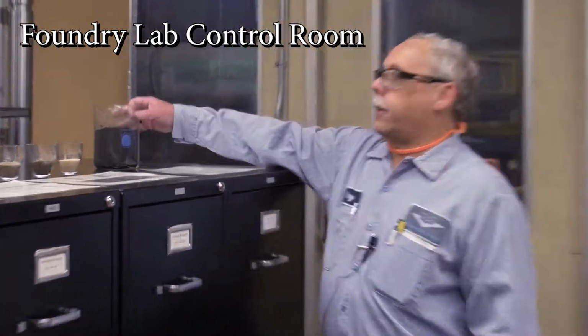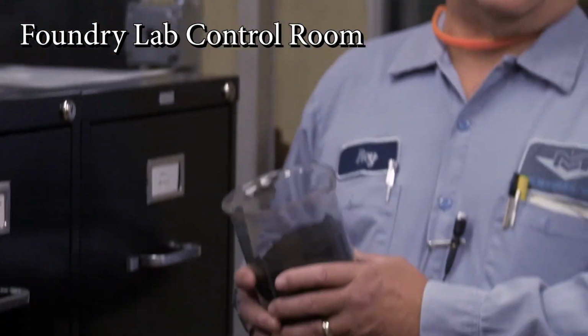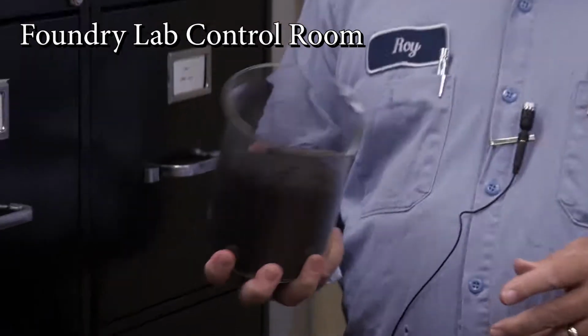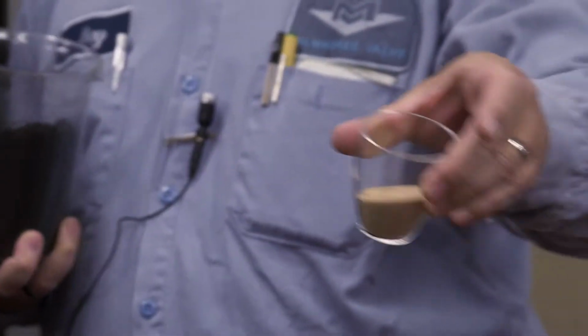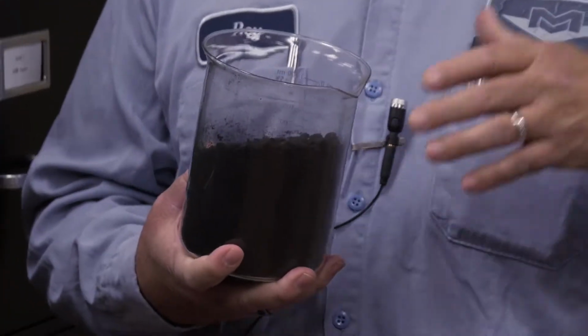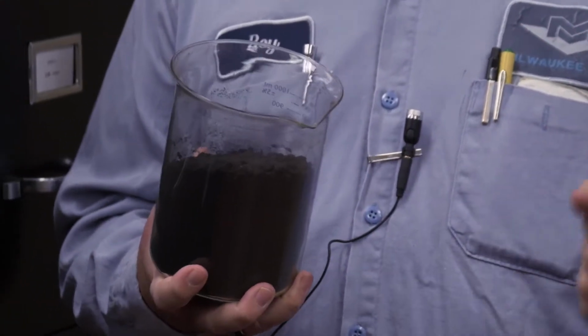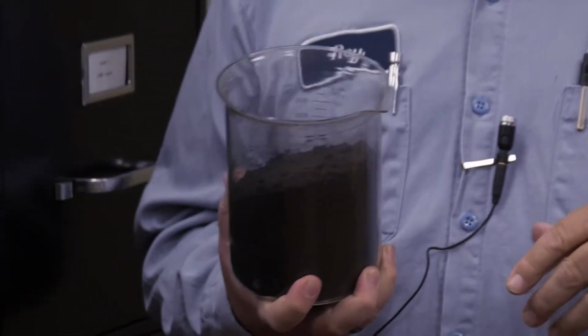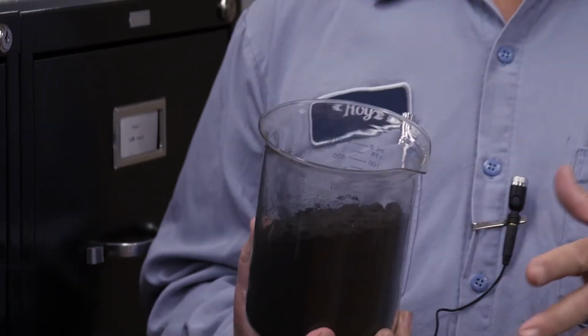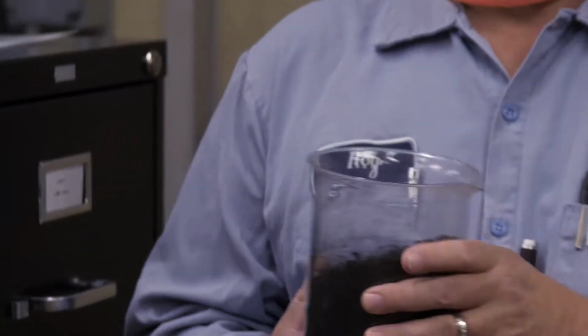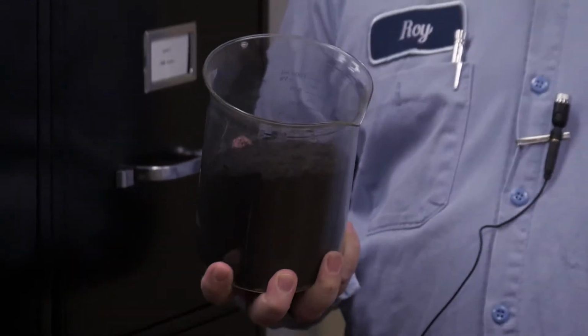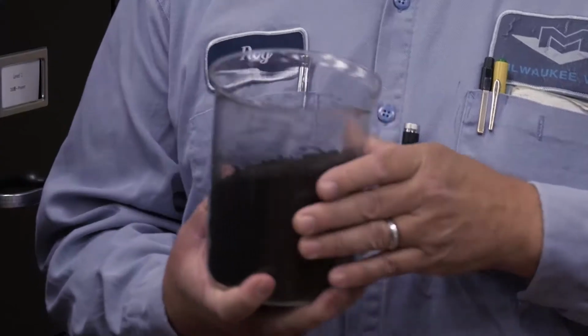The foundry process, our main molding line is with green sand molding, and this is the sand we use for molding. It's silica sand, which comes in very much like this, white silica sand like you'd see on the beach almost. And then we will coat it with clay, and that's where it gets the black color. The clay coating gets burned onto each individual sand grain. And we mix it with water to bond the sand together so we can make an impression in the mold, and in that impression we'll pour the casting.